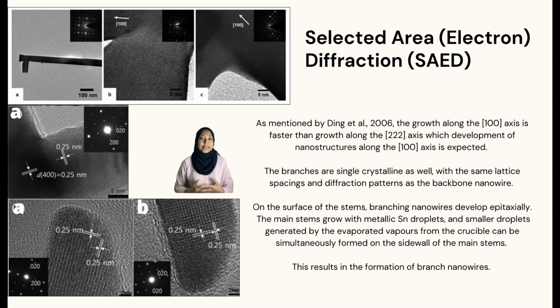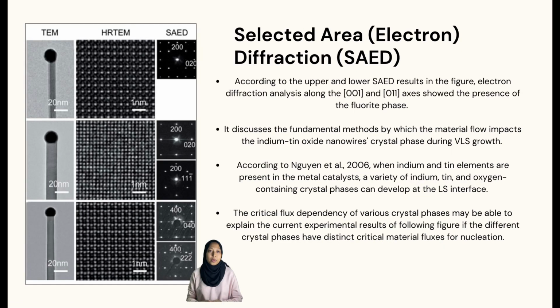As mentioned by Ding et al., 2006, the growth along the 100 axis is faster than growth along the 222 axis, so development of nanostructures along the 100 axis is expected. For the second figure, the branching nanowires develop epitaxially on the stems. The branches are single crystalline as well, with the same lattice spacings and diffraction patterns as the backbone of the nanowire. From the figure, electron diffraction analysis along the 001 and 011 axes showed the presence of the fluorite phase.